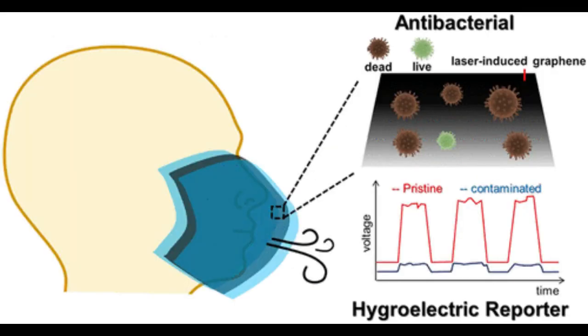but he believed it might be related to the damage of bacterial cell membranes by graphene's sharp edges, and the bacteria may be killed by dehydration induced by the hydrophobic, water-repelling property of graphene.